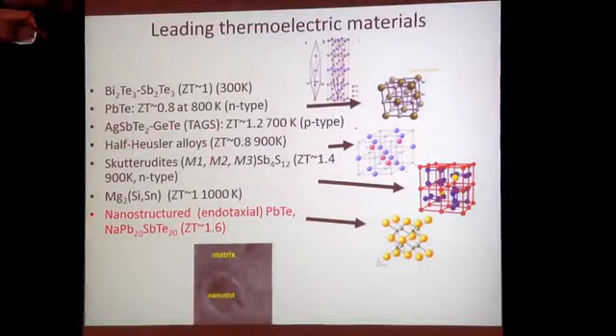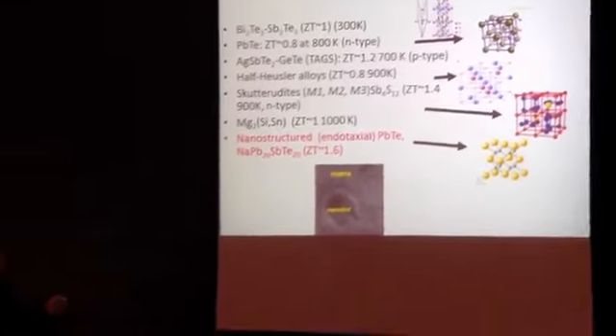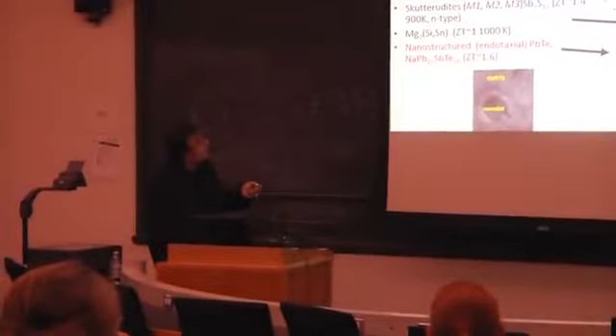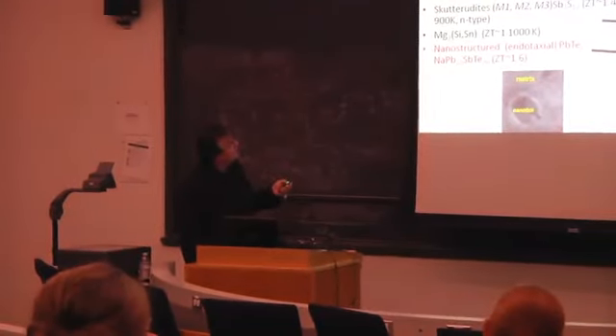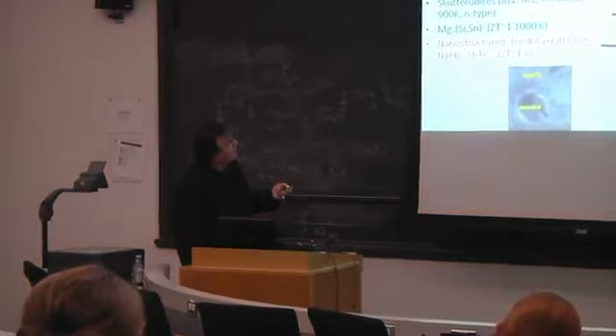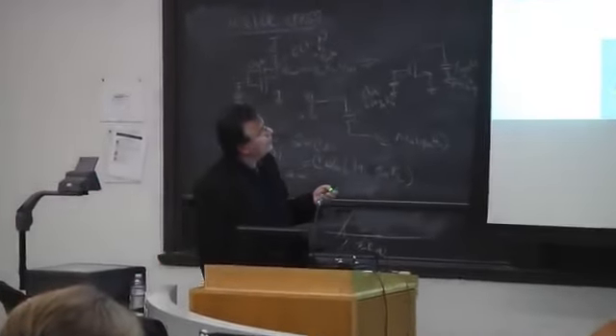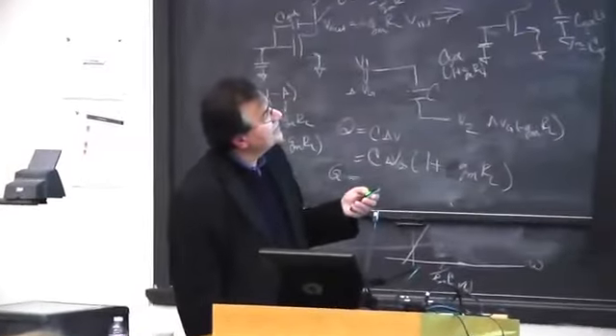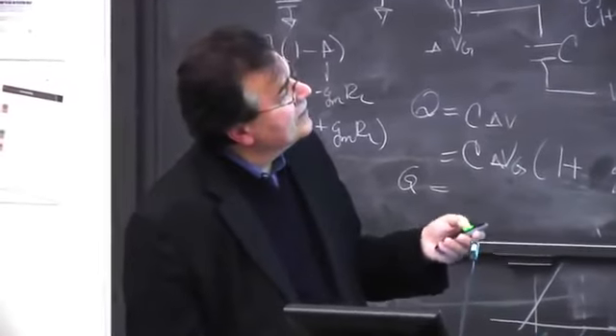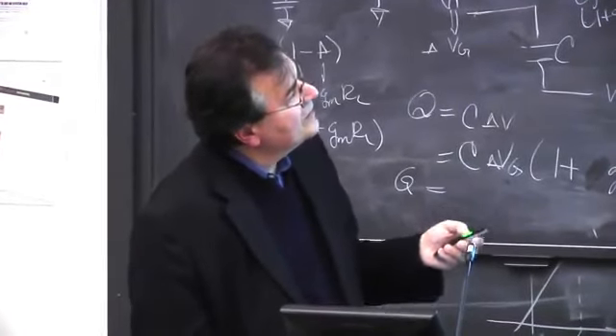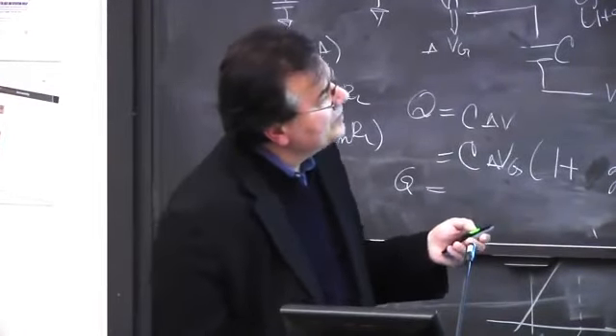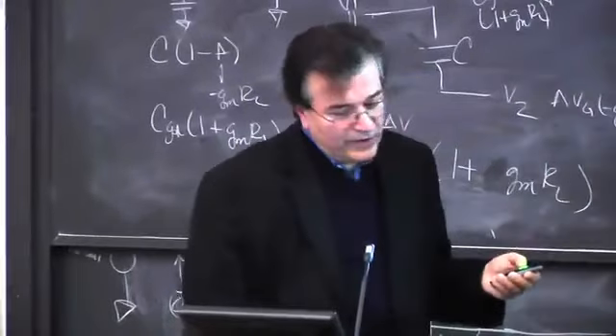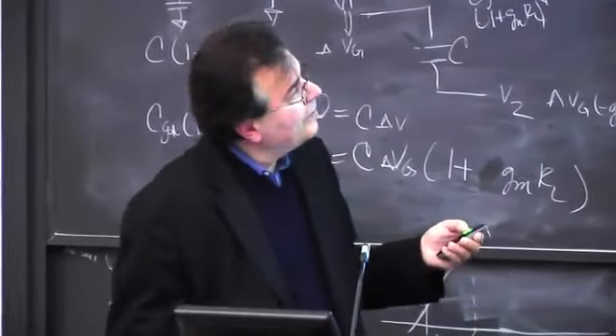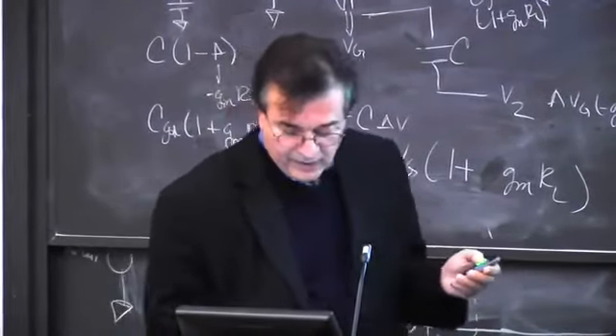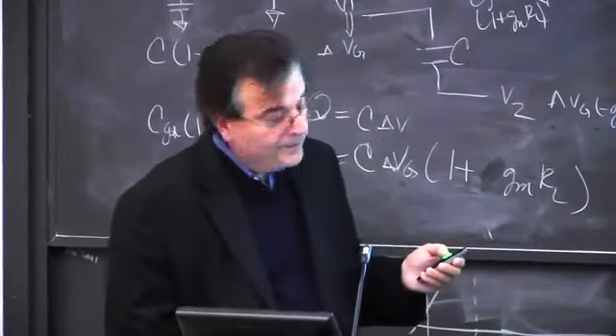Half-Heusler alloys, there's a community working with them. Best ZT of about 0.8 at 900 Kelvin. The skutterudites that have come along lately with a ZT of about 1.4, 1.5 at high temperatures. These are all pure phases, single compounds, magnesium silicide, and then the nanostructured materials that my group is doing as well. And I will focus on this the rest of the talk here.